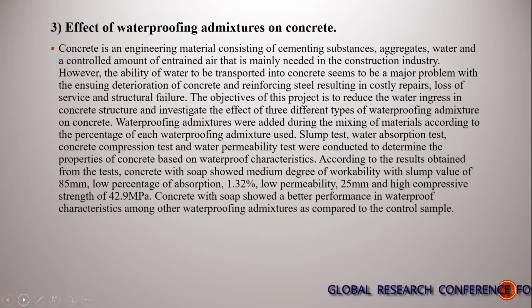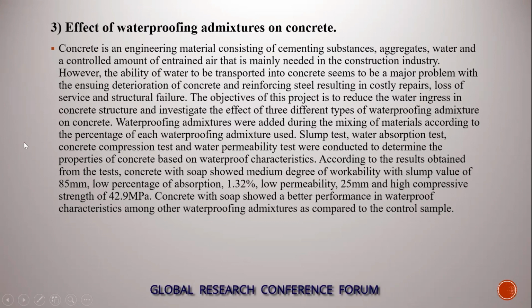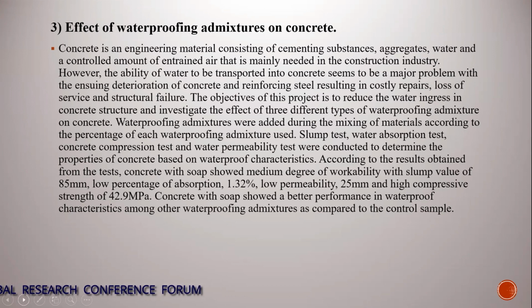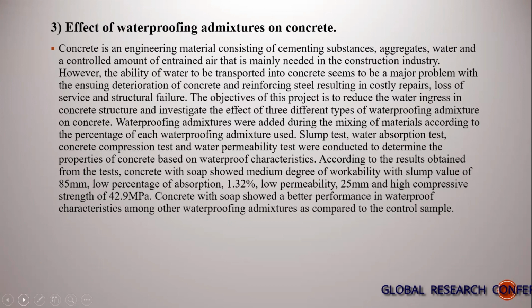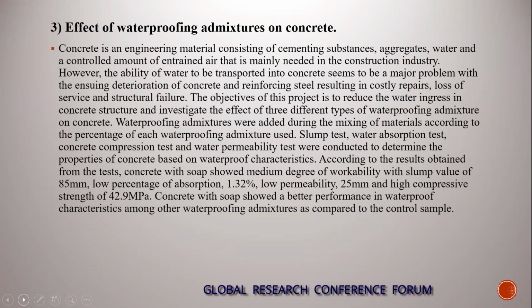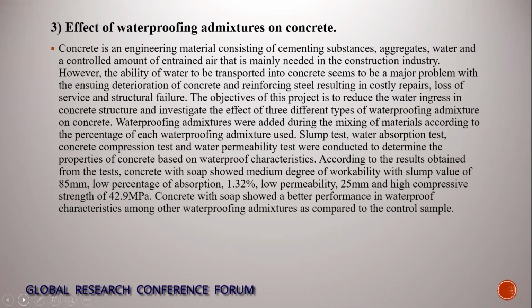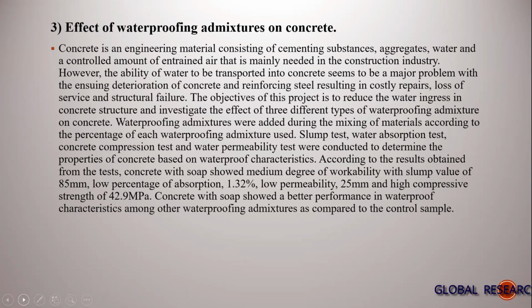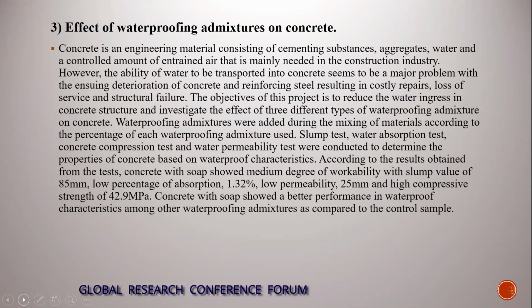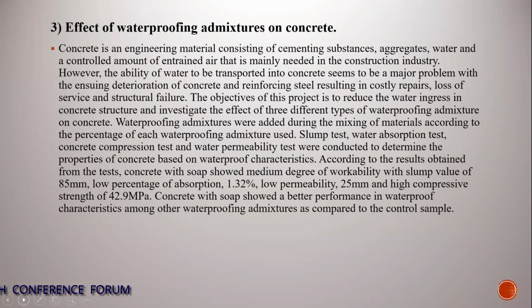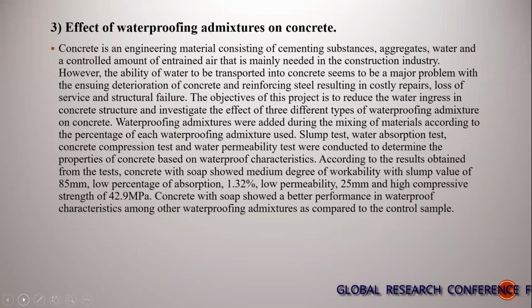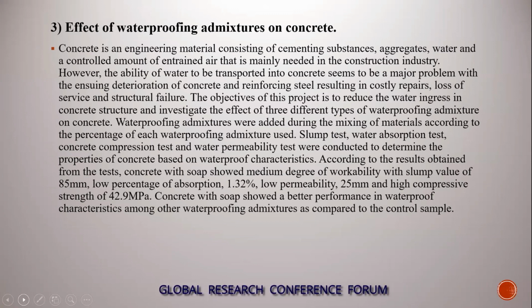According to the results obtained from the tests, concrete with soap showed a medium degree of workability with a slump value of 85 mm, low percentage of absorption, 1.32 percent, low permeability, 25 mm, and high compressive strength of 42.9 MPa. Concrete with soap showed a better performance in waterproofing among the other waterproofing admixtures as compared to the control sample.